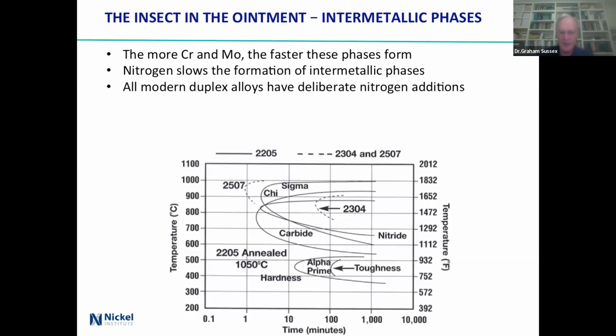If you've got lots of nitrogen, it's going to happen less rapidly, but it's okay because all modern duplexes have nitrogen in them. So what have we got there? We've got nitrides. That particularly happens with getting too much ferrite. Carbides, usually not a problem because we're looking at pretty low carbon in all of the duplexes. And then down the bottom, we've got the reason why you don't go above about 315 if you're looking at structural, because you're getting the 475 degree embrittlement. And those two lines there are 50% loss of toughness on the right and hardness on the left.